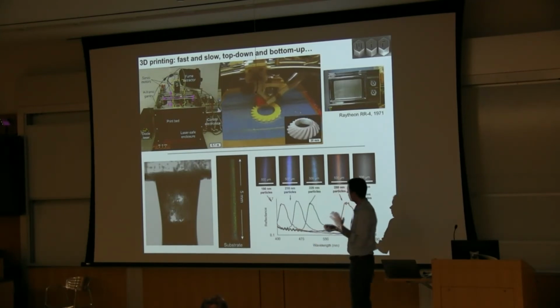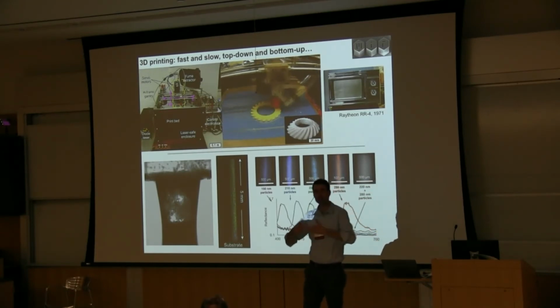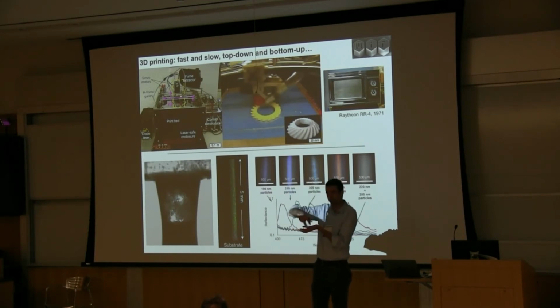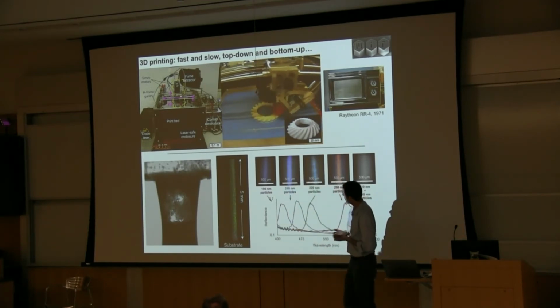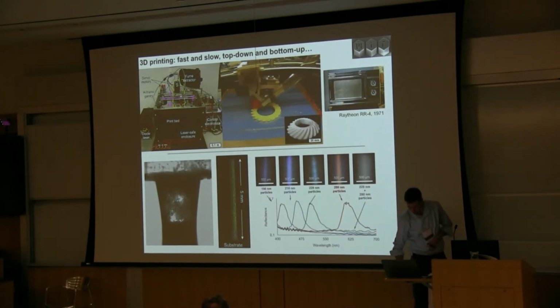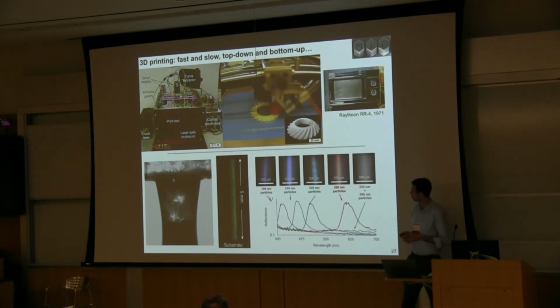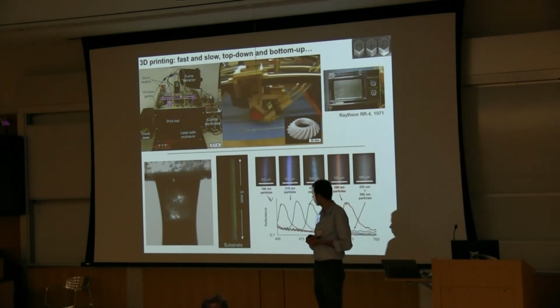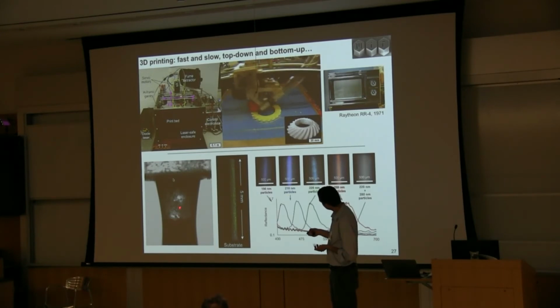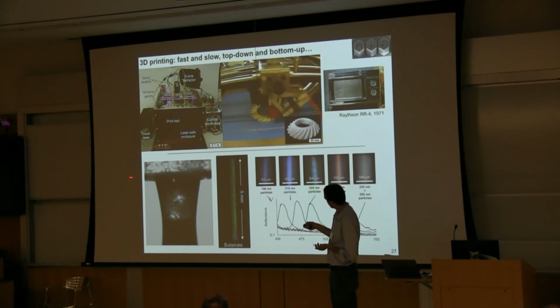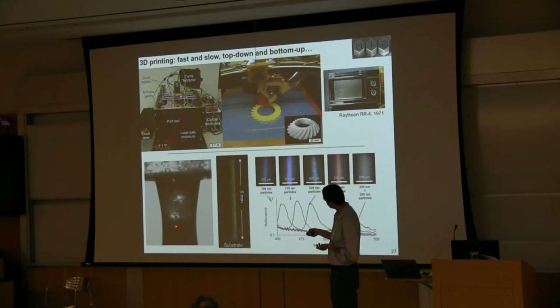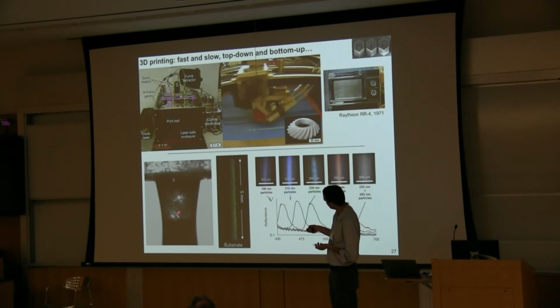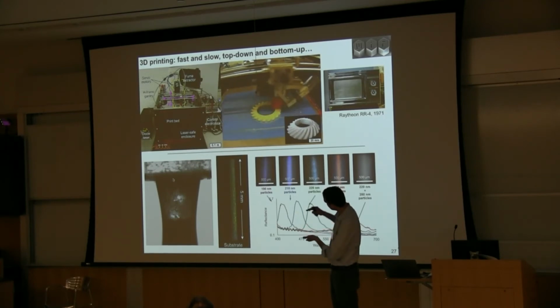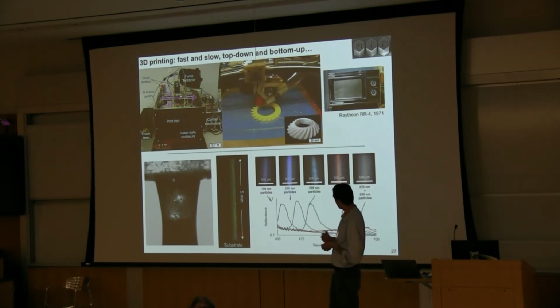We've also started to think about how to combine the principles of directed self-assembly or capillary directed assembly with the principle of 3D printing and extrusion. These are some recent experiments where we, with precision, do something very simple, which is we take a colloidal solution of microbeads, of polymer beads, and we slowly extrude them out of a moving needle. So what you're seeing here is a fine glass capillary, and a solution of polystyrene spheres being drawn down by evaporation-driven convection. As we move these apart, we can grow fairly tall colloidal crystals, polycrystalline colloidal structures up to a few millimeters or even a couple centimeters.